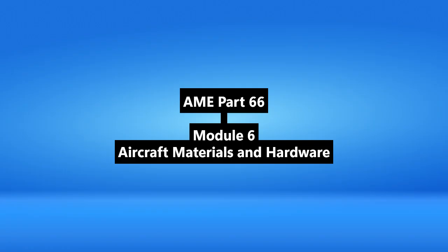That makes sense. So how do they find these hidden flaws? Can't just look at the surface, can you? Not reliably. Non-destructive inspection (NDI) is crucial. Visual check is first, looking for whitening, maybe indicating subsurface issues, but it's limited. What else? Tap testing or coin tapping. Simple, rapid for large areas. Listening for the sound. Exactly. Solid structure rings clearly. A dull thud can indicate a near-surface delamination or void. There are even automated tap testers now.